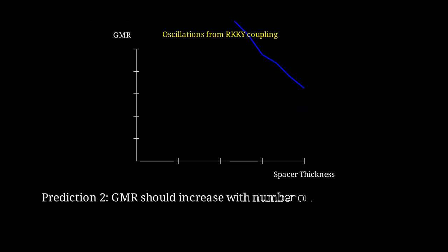Prediction 2. GMR should increase with the number of repeating bilayers, then saturate. This is because more interfaces mean more spin-dependent scattering events. However, it saturates because electrons can only maintain their spin orientation over a finite distance called the spin diffusion length, typically 10 to 100 nanometers. The spin diffusion length lambda SF equals the square root of D times tau SF, where D is the diffusion constant and tau SF is the spin flip time.